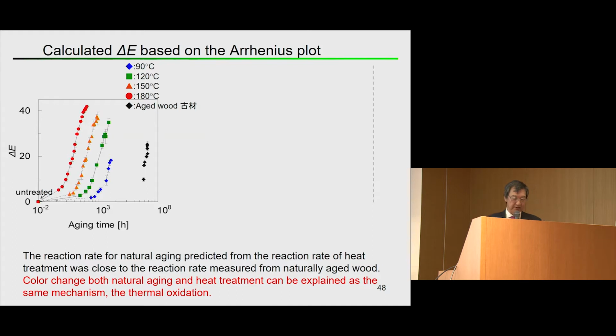This is the result of the delta E based on the Arrhenius plot. Here you can see the 90 degrees Celsius heat treatment, 120, 150, 180 at various heating times. You can see here the aged wood as well, so that the color values change faster with increasing temperature and aging time in systematic order. We found the color change in both natural aging and heat treatment can be explained by the same mechanism, and that is thermal oxidation, which means the color change actually obeys the Arrhenius law.